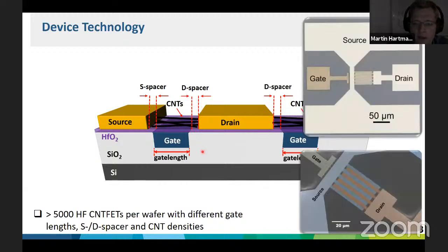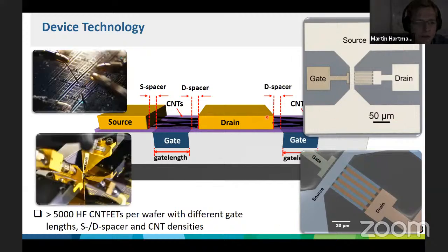And when you take a look at the devices here, they look like that. So we fabricate them in a ground-signal-ground configuration to do the high frequency measurements. And after they are done, we make DC measurements on the entire wafer of the transistors, and then the colleagues at TU Dresden measure the high frequency performance, so the S parameters, the scattering parameters of our devices.